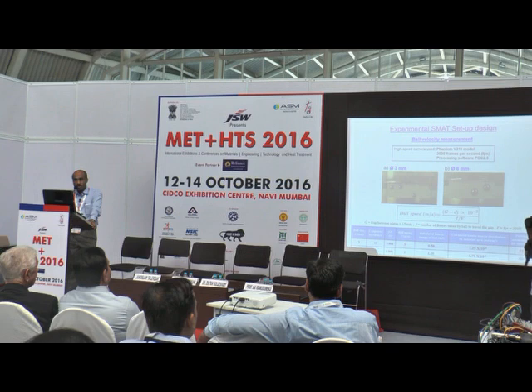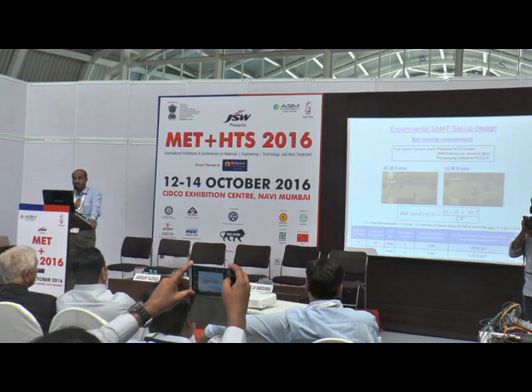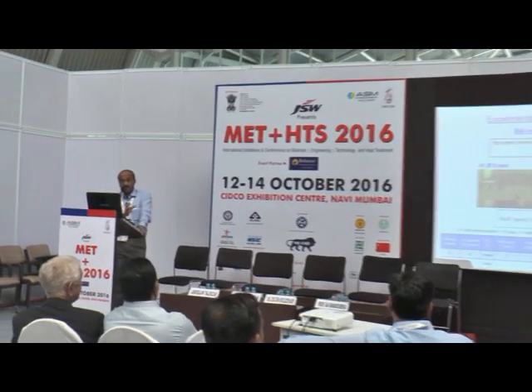Here it is important to know the velocity of a ball. This velocity depends very much upon the size of the ball, because depending upon the ball size you have different kinetic energy transferred to the specimen. At the same time, this velocity decides how many times your specimen surface is going to be impacted by the vibrating balls. So in short, there are multiple SMAT parameters, and these multiple factors should give some conclusive understanding that helps explain the microstructure evolution in the material.